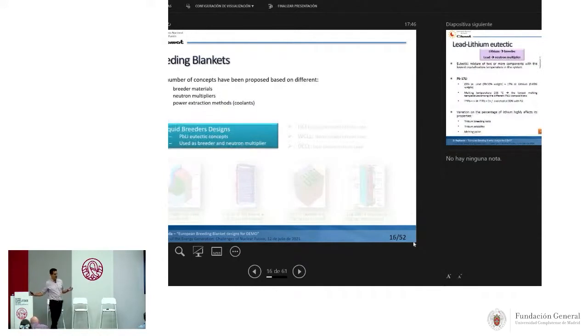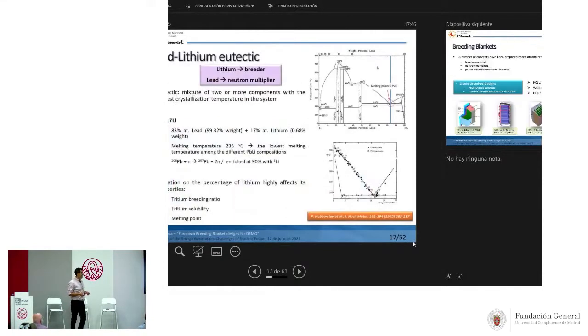The second family of blankets is composed of liquid breeders. In this case, what we use is the eutectic alloy of lead lithium, which is a metallic alloy, where the lithium acts as breeder and the lead is the neutron multiplier. Among the different eutectic compositions that this alloy can have, we have used this one, 83% lead and 17% lithium, because it presents the lowest melting temperature of all the compositions.